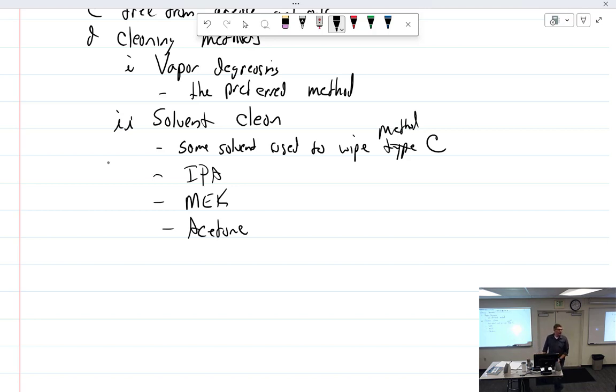Kerosene? Would kerosene work? If it degreases it, but that's an oil product. True. So I worry about that one. You don't want it to be an oil product. And you have to consider that it should be something that dries quickly, because any solvent that gets into a crack displaces penetrant. So it's important that it flashes out and dries quickly.